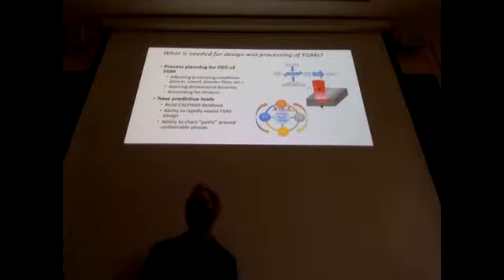So if you're assuming that you're getting a bead height of, let's say, 1 millimeter, you want to be able to maintain that all the way across, no matter if you're depositing material A, a mixture of material A and B, or material B by itself. You always want to make sure that your overall process is consistent and your dimensions are consistent of that bead geometry. And then the other thing you want to do is account for dilution. So if you're trying to hit certain targets and maintain a chemistry within certain limits, it's important to understand that dilution level as well. So that was one area that we felt like we needed to concentrate on.